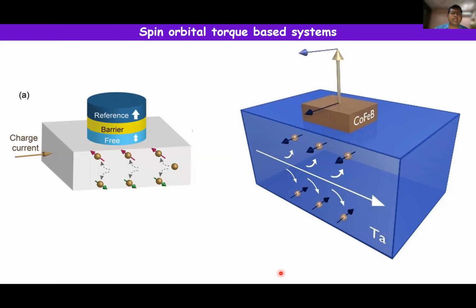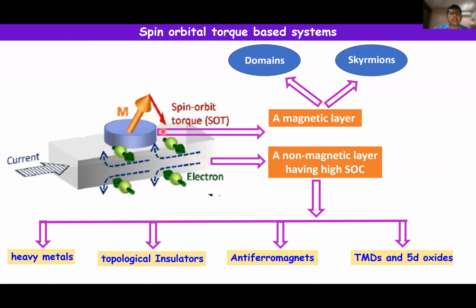Now, as I said in the beginning, in this kind of spin orbit torque based device, there are two components. The bottom component is the high spin orbit coupling material, and the top component is the ferromagnet. So you can define the system like component A, component B, where component A is something with high spin orbit coupling, and we are looking for alternatives. These alternatives are other heavy metals also, like tantalum, tungsten, and so on. You can create these beta phases, and they exhibit even higher spin Hall resistivity and spin Hall angle. Or you look for other possible quantum materials.